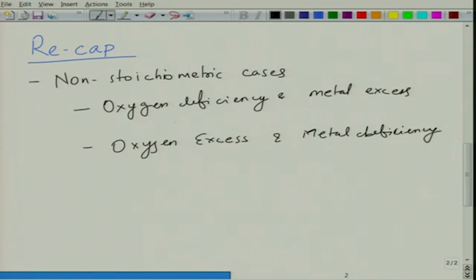right. So, the first one can be determined as MO1 minus X, this could be M1 plus XO, this could be MO1 plus X, and this could be M1 minus XO. Okay. So, essentially in the first case you form vacancies of oxygen, and they can be compensated either electronically by forming electrons, or they can be formed by reduction of metal at metal sites.